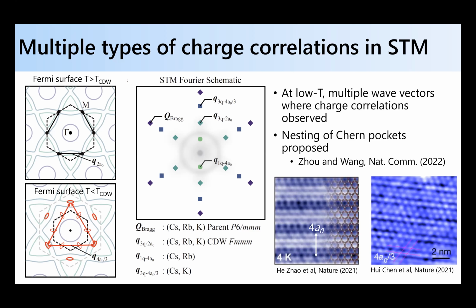And so if I look at the Fourier transform of what they see on the surface in terms of charge correlations, what they see basically are these 1D 4A0 type of correlations. These are the 2x2 correlations. And then there's this intermediate 4/3 A0 correlations. Along this wave vector, in the superconducting state, the superfluid density seems to be modulated along this wave vector. And it's another 3Q order.